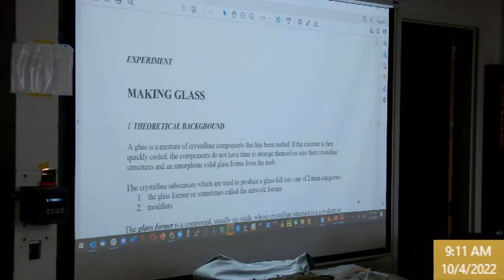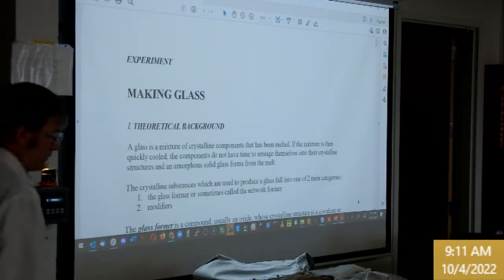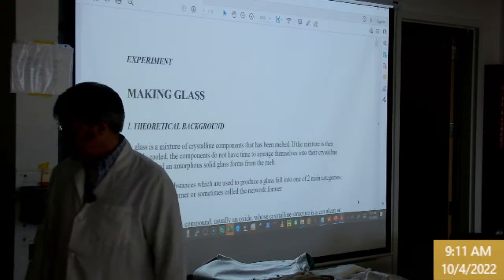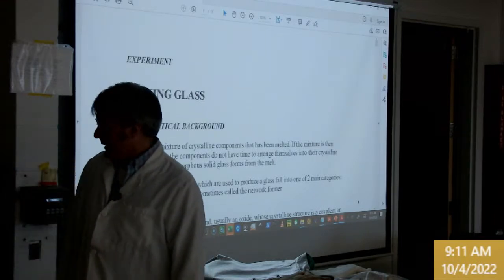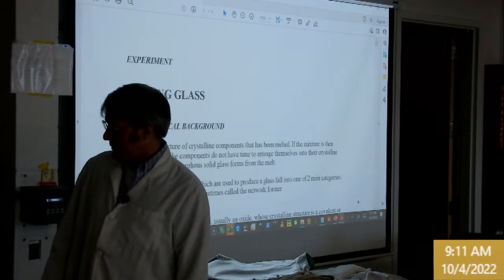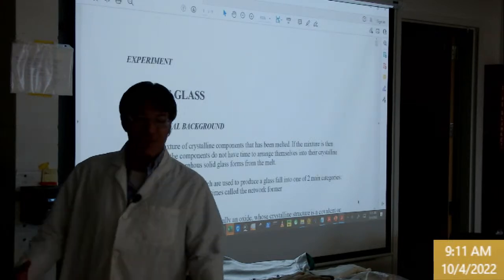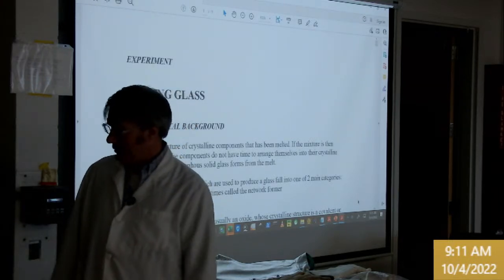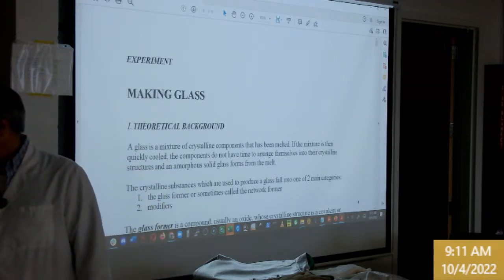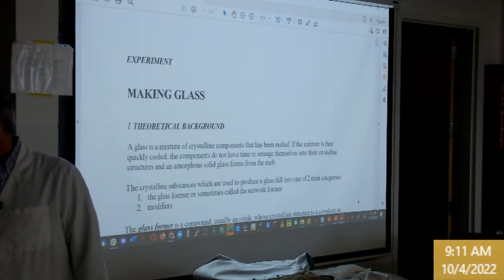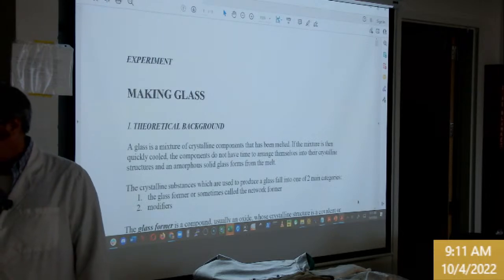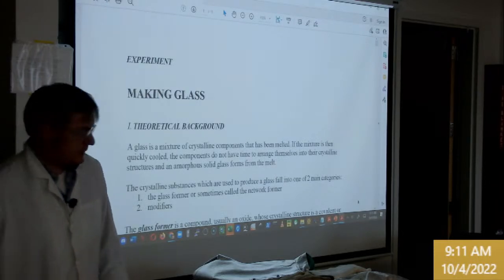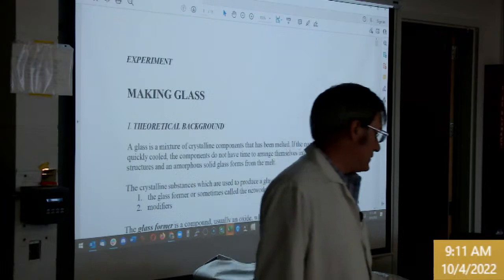What I noticed in the spring was that our glass looked a little bit more viscous than it did the previous years. We recently transitioned from this furnace, which you can see is battle tested. It's got some heating element issues and I can't find replacements. So I'm either going to have to scrap it or make my own elements. So got to figure that one out. I usually like to have some backups, which is why I'm still thinking of that one. But still dialing in that temperature. So we're going to bump that up. It should be ready to go here in a few minutes.